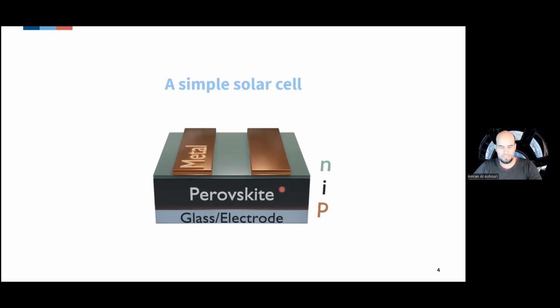So then you can do the investigations of the interfaces that are extremely delicate, as people have found out in literature as well. Usually the perovskite is not the problem, but the interface to the charge selective layers is. In PIN solar cells, the N-type layer is mostly constant, so it's fullerenes. I've also explored a lot of alternatives, but there's nothing like C60 or PCBM. They just win in most cases.